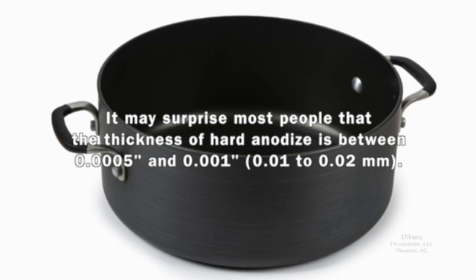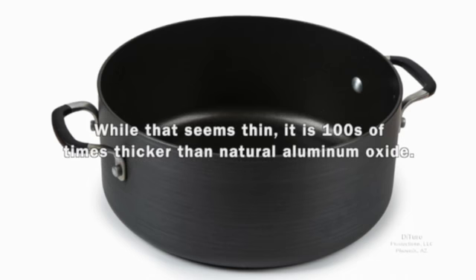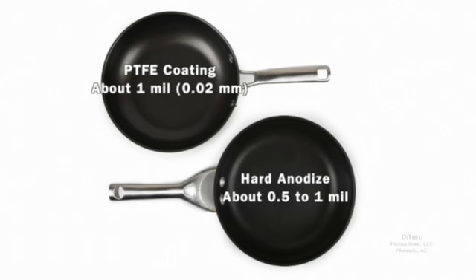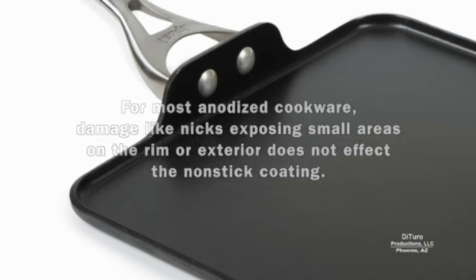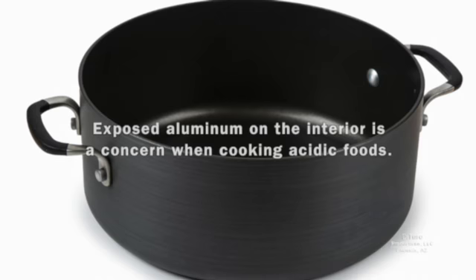It may surprise most people that the thickness of hard anodize is between half a thousandth and one thousandth of an inch. While that seems thin, it's hundreds of times thicker than natural aluminum oxide. The thickness of PTFE and hard anodized coatings are about the same. For most anodized cookware, damage like nicks exposing small areas on the rim or exterior does not affect the nonstick coating. Exposed aluminum on the interior is a concern when cooking acidic foods.